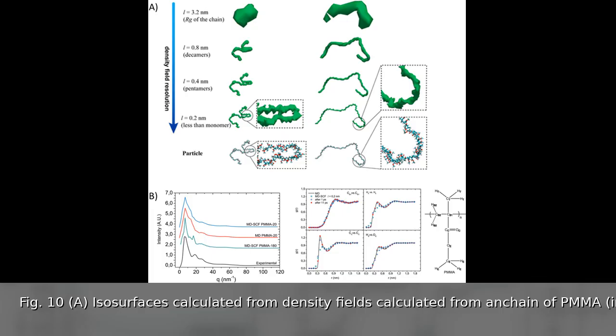atomistic data. Panel A illustrates an equilibration procedure involving successive MD simulations with progressively finer density grid resolutions applied to polymethyl methacrylate, PMMA. This multi-resolution approach enables the generation of all atom structures that reproduce key structural correlations observed in extended fully atomistic MD runs, but at substantially reduced computational cost. Panel B compares radial distribution functions from HPFMD and long conventional simulations, demonstrating the ability of HPFMD to capture subtle chemical structure details when suitable grid resolution is chosen.